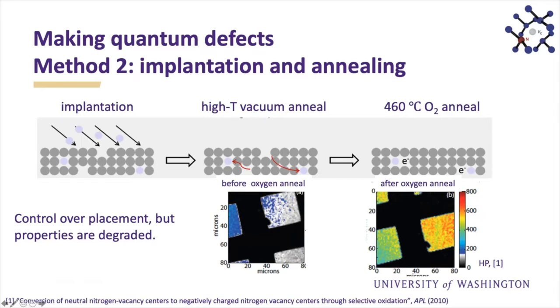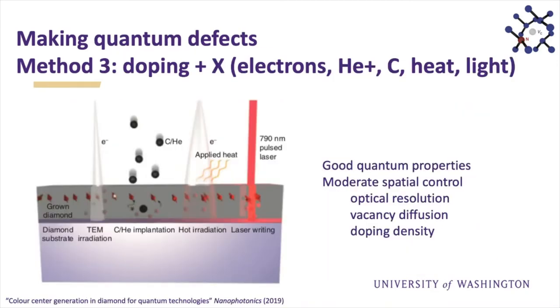These defects can also have a charge, and the particular charge we want is the negative charge. And so we do another step here where we oxygen anneal, and spectrally you would see that we converted the charge. Qualitatively, just from these microscope images, you can see they got a lot brighter, these defects. And what happened here is the oxygen anneal enabled us to capture an electron and have the right charge state for these defects that we created. So this has the highest control over placement, but the properties are degraded. And that's the optical stability and the quantum memory time.